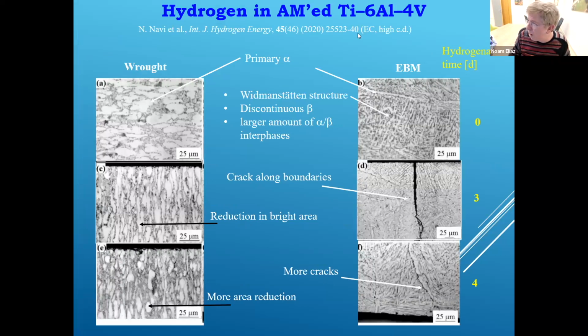So just to show you from our published papers on the titanium 6-4, we always compare the wrought to the EBM. When we started this project some years ago, my hypothesis at the time was that I expected the additively manufactured alloys to be more susceptible, not always, but on average, to hydrogen damage than the wrought alloys. At the time, there was no publication or report on this. So we started studying this systematically under electrochemical hydrogen charging, gaseous hydrogen charging, and the behavior is different.